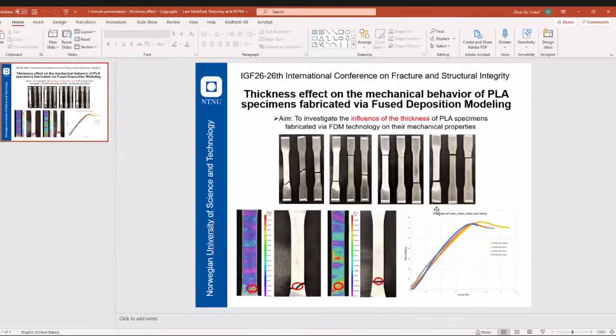So we used a Prusa i3 MK3, if I remember correctly, and the maximum resolution for the Z axis is 50 micrometers, or 0.05 millimeters. The layer height we used in this research is 0.1 millimeter. We did some trial and error to adjust the printing parameters to get the infill percentage as close to 100% as possible, while maintaining the correct dimensions for the specimens, because we don't want any over-extrusion or under-extrusion during fabrication.